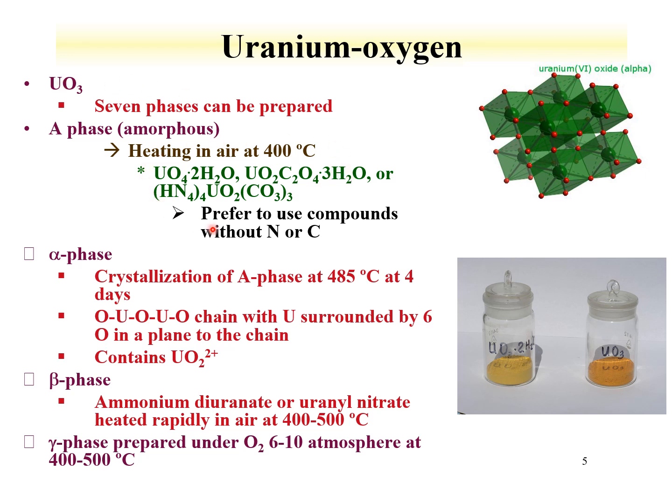And here's a number of compounds that can be produced, oxalates, carbonates, that can be heated to 400 degrees, which makes the UO3. We can change the crystallinity by changing the temperature. This is often done in the laboratory. If we want to make compounds with different crystallinity, we'll often try to anneal them at a temperature so that the crystal structures form. And the reason that we're interested in getting crystalline compounds is that we can then determine them by X-ray diffraction.